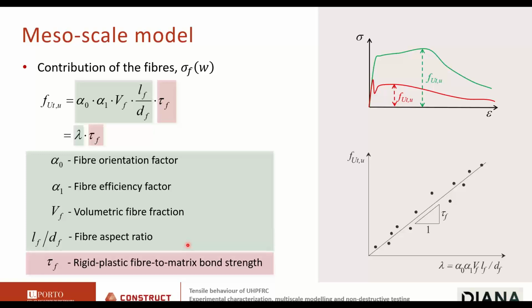Let's look a little bit at this equation. So you see here a product of two parameters that depend on fiber orientation, but still related to fibers. The fiber content, the fiber volumetric fraction, okay. The fiber aspect ratio, so the length of the fiber divided by the diameter. So all this is fiber related. This can be lumped in a single scalar value, what we call the fiber structure parameter. And this is the rigid plastic fiber to matrix bond strength that depends on the matrix and the shape of the fibers. So if this equation is correct, then I can plot the tensile strength as a function of the fiber structure parameter, and I would expect a straight line with the slope being the bond strength.